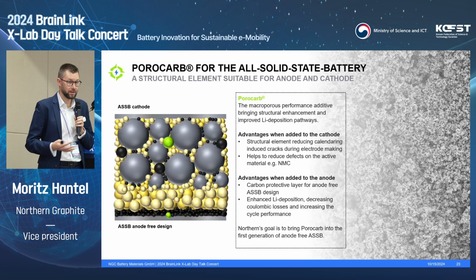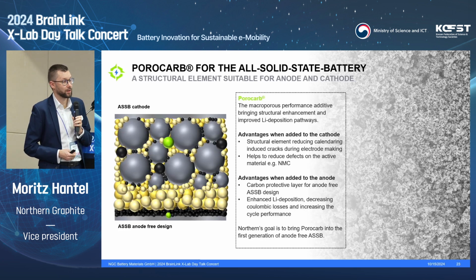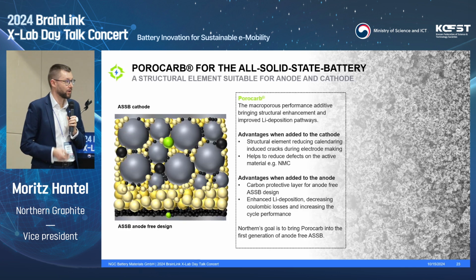They avoid crack building already in the production process, which on the contrary also helps to form fewer cracks in the active material and has a better utilization of the active material. On the other side,